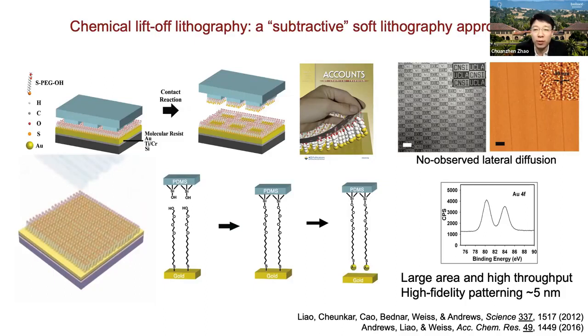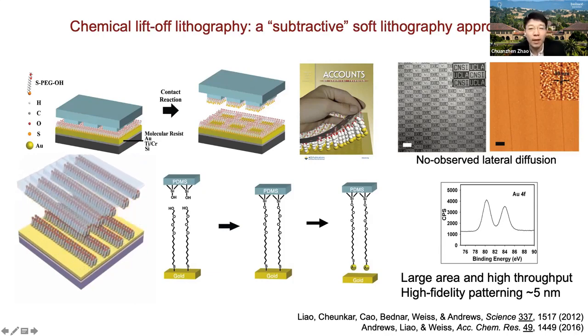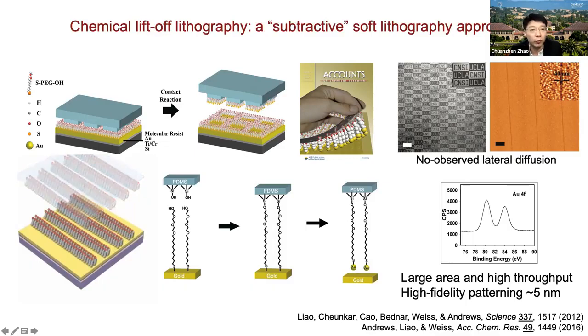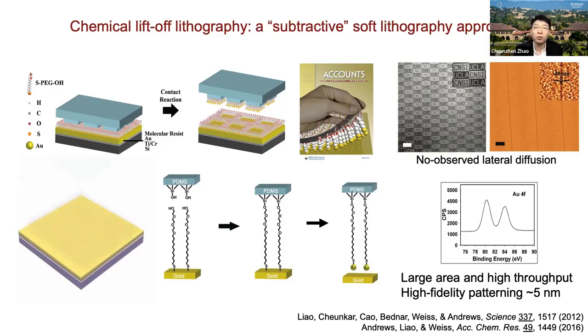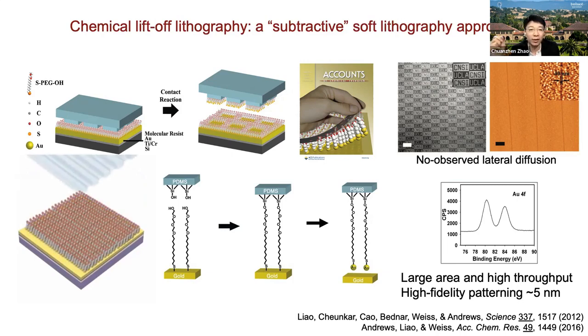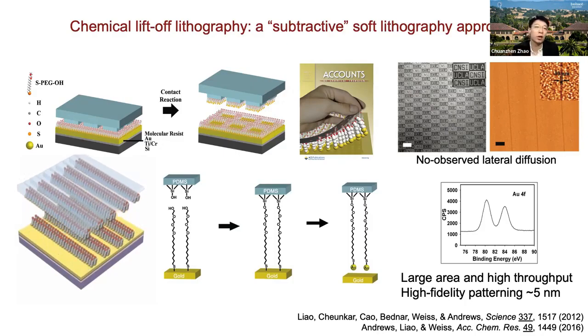So this process can produce high pattern fidelity and we didn't observe any lateral diffusion. It has been shown to reach resolution down to 5 nanometers, which is around 10 gold atoms across. A layer of gold atoms will also be removed from the surface, as confirmed by the XPS data shown here. With this approach, we were able to pattern micron and nanoscale features at large scale with high throughput. Our group has been working on advanced CLL techniques for higher resolution and also exploring its application in a variety of fields, which I will talk about some of them today.